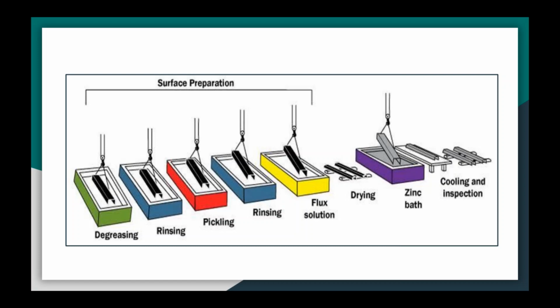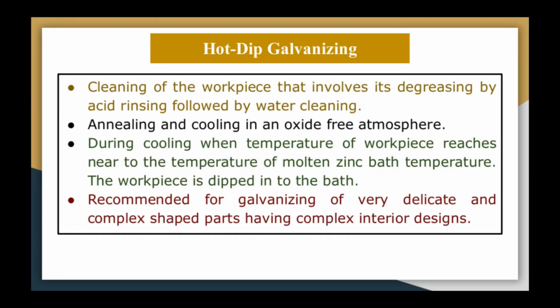A number of methods can be employed for galvanizing zinc to the metal substrate. So accordingly, we have different galvanizing methods. So first is hot dip galvanizing. The first step of this process is cleaning of the workpiece, that involves its degreasing by acid rinsing followed by water cleaning, and the second step is its annealing and cooling in an oxide free atmosphere.